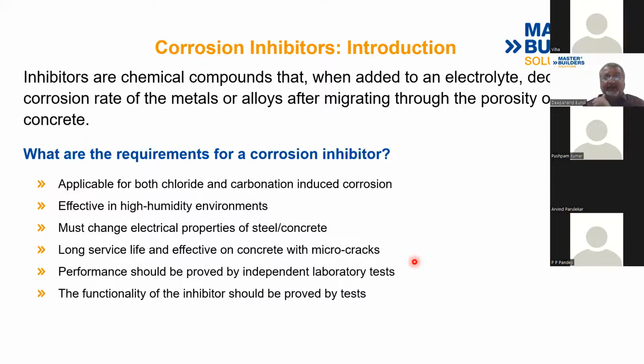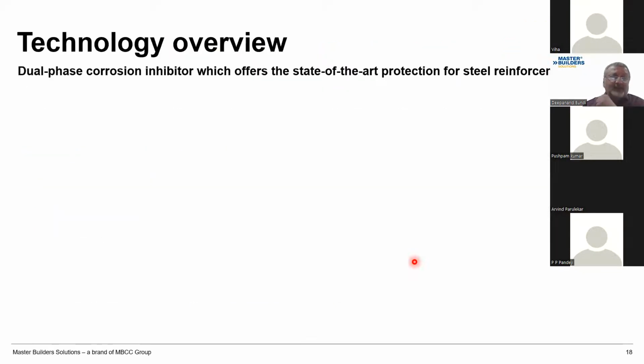and should be effective on concrete which is having cracks. So maybe after you cast your concrete wall or a retaining wall or a structure, concrete is going to crack, it's a brittle material. So I should have my protection that should be able to prevent the corrosion even after the concrete has cracked. The performance should be proven by lab tests, and the functionality of the inhibitor should be proved, of course, at site itself.